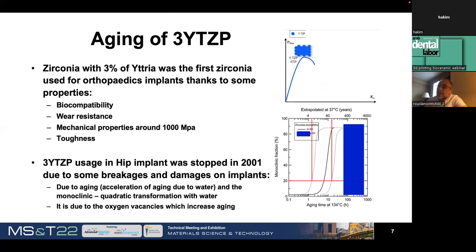When you do the simulation, and this is done in this field, of this aging of 3% yttria zirconia, we can see that usually the test is done at 134 degrees C, and depending on the time you see this degradation, you can calculate the theoretical extrapolated time of aging at low temperature at 37 degrees, human body temperature. And you can notice that 3% yttria zirconia lasts less than 10 years. You can see this on this diagram, which is in the bottom right corner of the slide.